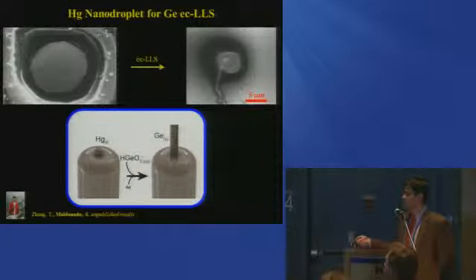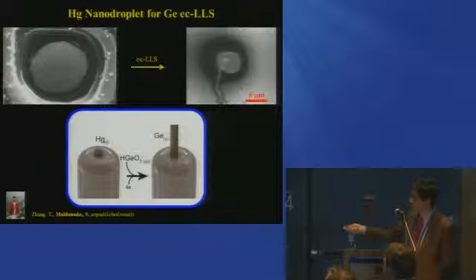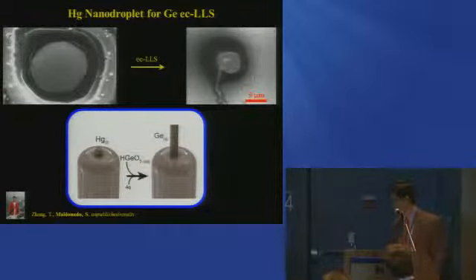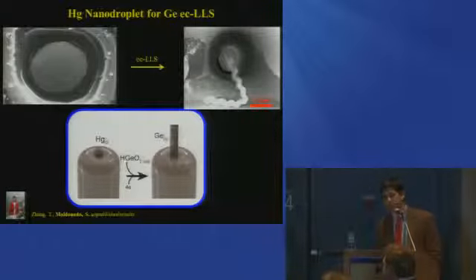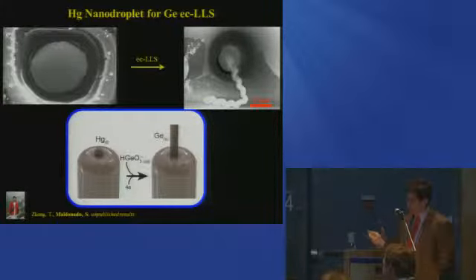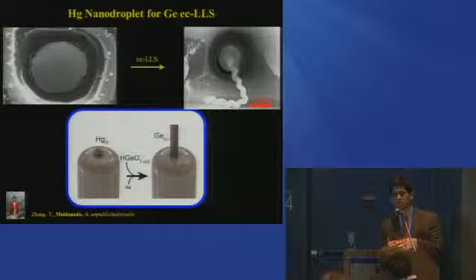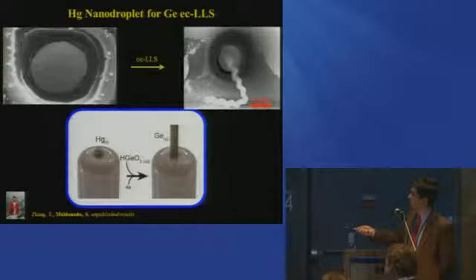We've done this experiment, or actually Tim has done this experiment several times, and we get, on average, some things that look like this. So here's a before and after experiment. Here we've electrodeposited on a mercury ultramicro electrode, not a single, but relatively few filaments coming off, which end up being crystalline germanium. We've actually done this experiment a lot, and we haven't published this for the reason that we've found that it's not quite stochastic, but it's very hard to predict. And our working hypothesis right now is that what you get out of here is highly dependent on the initial stages of nucleation in the system, which we still don't really know how to control, but we have some tricks that we're trying to explore. But it turns out that this system that you can control electrochemically is a really good process for making wires in a rather unusual and unique way.